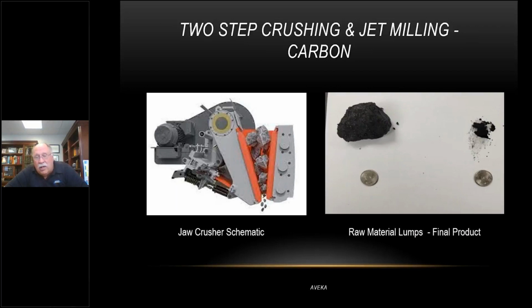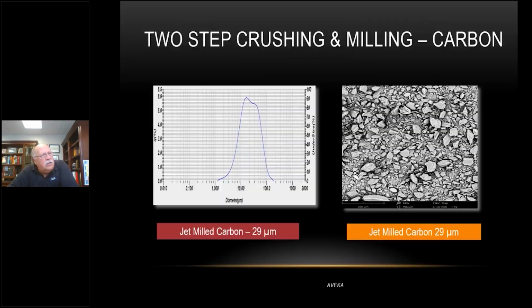And these are used in battery applications where we first jaw crush the material. And then finally, after we jaw crush the material, we had these big lumps that we started with, as shown here on the left side or the right side of the screen. And we were actually able to feed that fine powder into the jet mill to get a distribution that looks like this. So this is not quite as fine as the glass product. It wasn't needed to be as fine. We could have actually ground it to a finer size and classified it tighter, but you can see that we've gone from things that you're not going to measure with the laser diffraction system to a nice distribution.